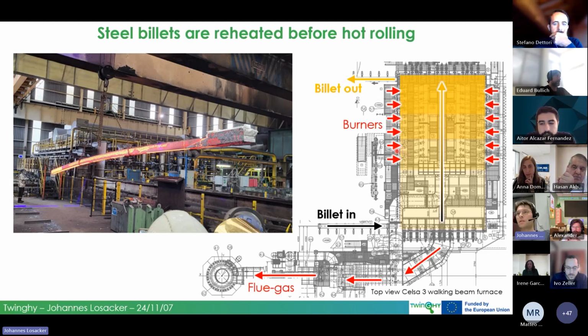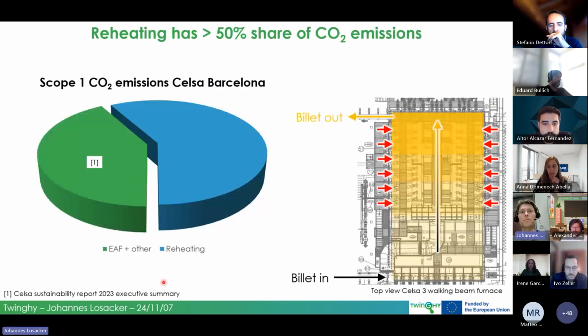You see them depicted here by the red arrows. There are 24 burners in total, 12 on the right and 12 on the left side. These burners burn into the combustion chamber and produce hot flue gases that transfer their heat to the billet. The flue gases then leave the combustion chamber down here to the central recuperator, where the off gases that are still hot preheat the combustion air, which is nice for an energy efficiency increase. The cooled flue gases then leave the system via the exhaust through the chimney.